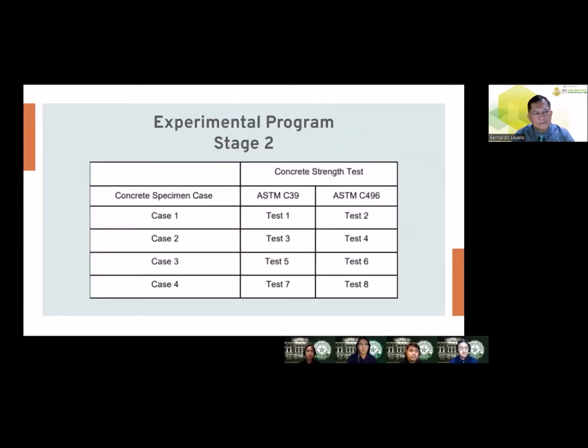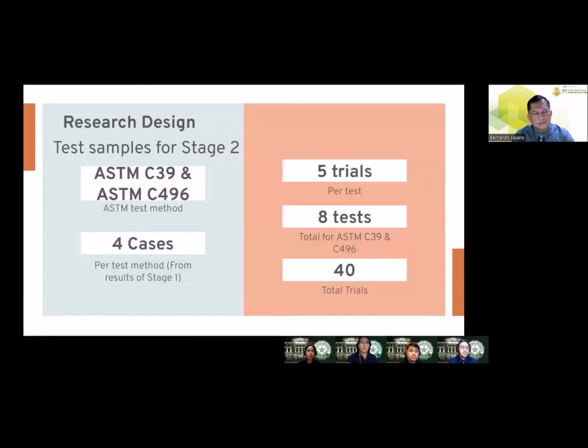Now, for stage two, each case refers to the chosen water to cement ratio of the previous stage. As seen for each case, a compressive strength test and a split tensile strength test is required. From the previous table, there are 4 cases per strength test, and 5 trials were conducted for each case, which totaled to 40 total trials for stage 2.